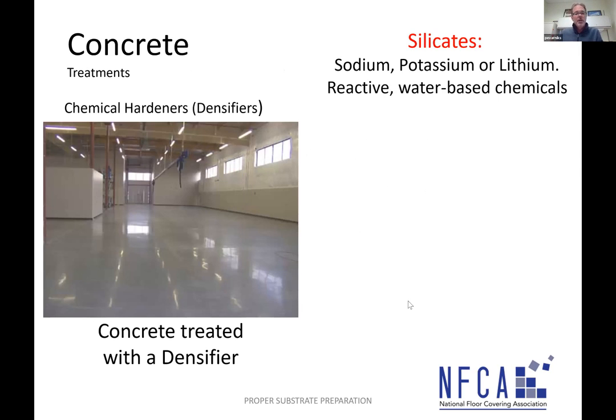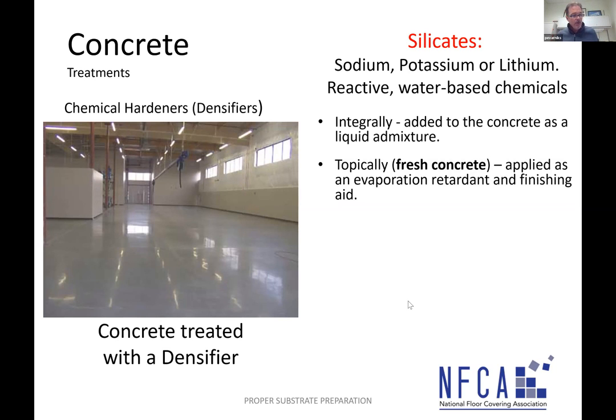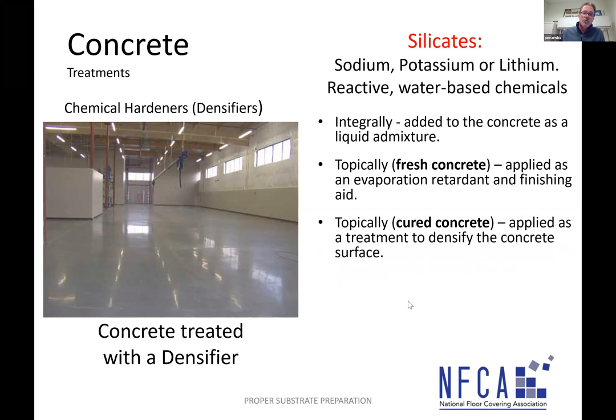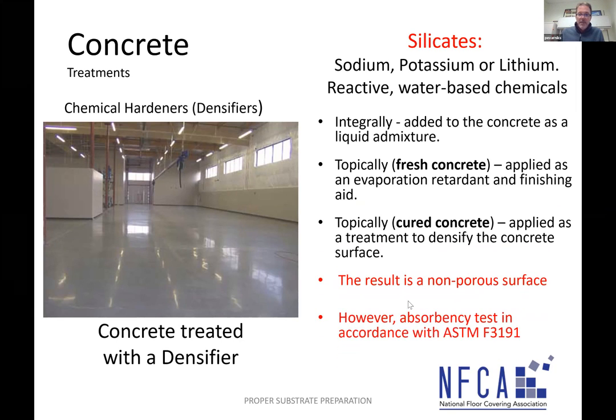So this is silicate treated concrete here. Sodium, potassium, lithium materials. They can actually be added to the mix into the concrete itself during placement. They can actually be topically applied to the concrete, act as a finishing aid, and they can actually be applied to concrete that's years old to densify the concrete, okay? When these silicates react with the calcium hydroxide and create more calcium silicate hydrate, they're densifying the concrete. They are making the concrete non-porous, non-absorbent, okay? And you can do an absorbency test, ASTM F3191, to see if that concrete is or isn't absorbent.